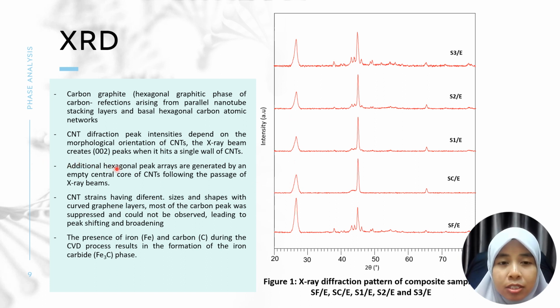So the additional hexagonal peaks arrays are generated by an empty central core of CNT following the passage of X-ray beams. And the CNT strains having different sizes and shapes with curved graphene layers, most of the carbon's peak was suppressed and could not be observed, leading to peak shifting and broadening. So we could see that this is actually broadened in the FWHM or full width half maximum. So it is broadened actually for the main or dominant peak of carbon graphite. And other than that is actually suppressed.